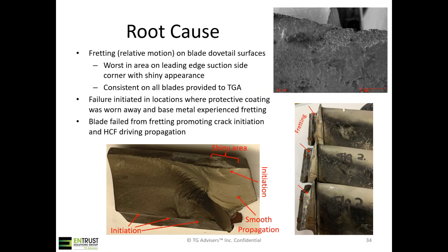So ultimately, the root cause, once we conducted metallurgical testing as well, ended up being fretting in conjunction with high cycle fatigue. Our initial thought when we saw that off schedule variable stator vane was just high cycle fatigue. But in this instance, these blades are a titanium alloy that's pretty commonly used in aeroderivatives. That titanium, 6 aluminum, 4 vanadium, is highly susceptible to